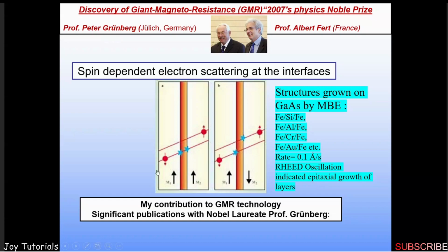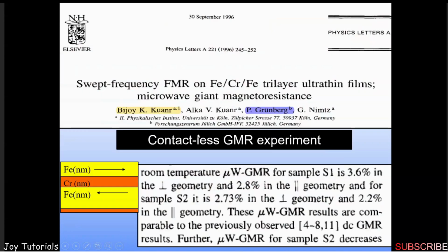Depending upon the spin-dependent scattering at the interface as well as in the bulk, one can have spin scattering, and from the structure, one can have the GMR effect, the GMR values. I'll just go through a few of our publications along with Peter. This is way back in '96. What we did is swept frequency FMR, ferromagnetic resonance, through which we have shown the giant magnetoresistance.